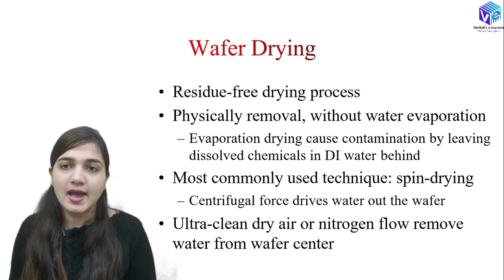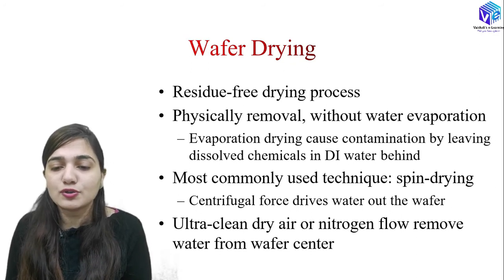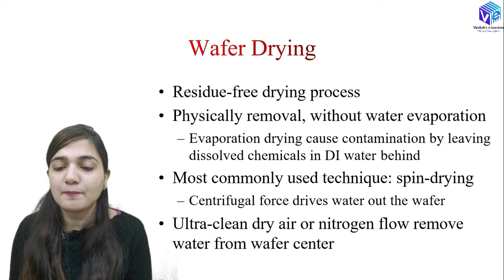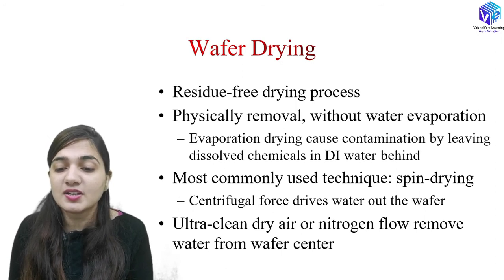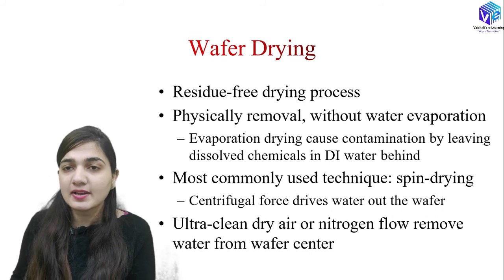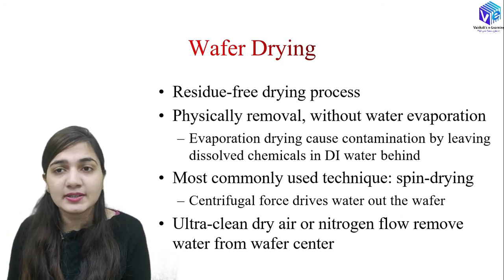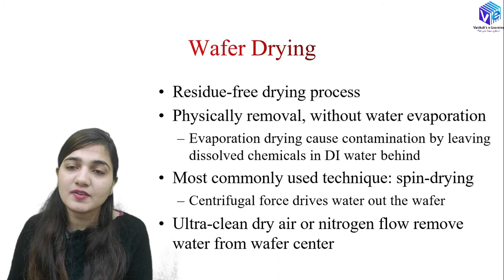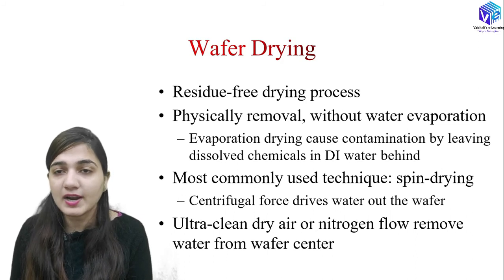Now coming to the wafer drying. I have now cleaned the wafer and rinsed it with deionized water, so now coming to the drying. We are going to do a residue-free drying process, physically removing all of the deionized water left on the wafer without water evaporation. Evaporation drying causes contamination by leaving the dissolved chemicals in the deionized water behind. When I evaporate the deionized water, the dissolved chemicals precipitate on the wafer and form contaminant particles, which reduces the wafer yield.